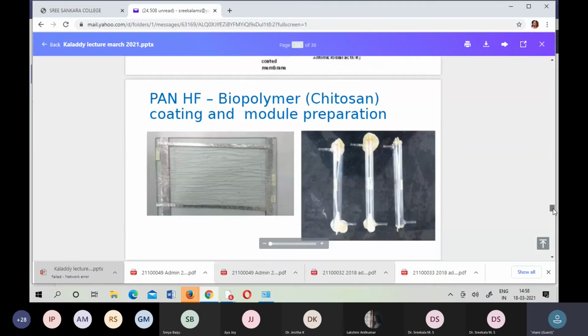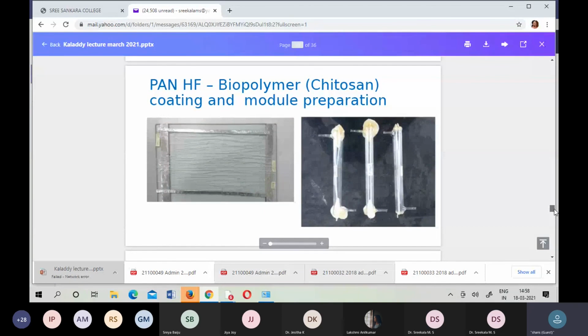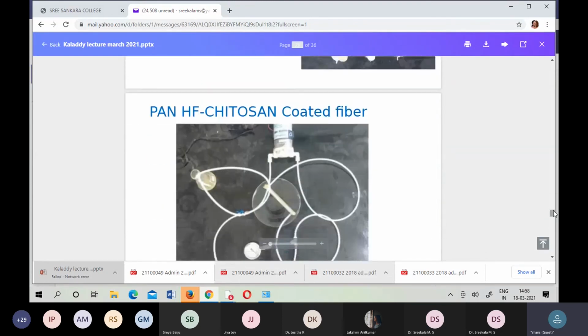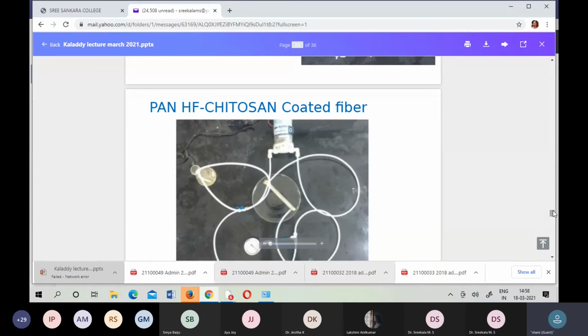Generally when you use only water, we get faster phase inversion and we may get a more dense membrane. But then in the last case we use DMF in water, 50-50. And the flow rate is also very crucial when you are making a hollow fiber. Flow rate in some cases is very high and in other cases very low, and that is the flow rate we maintain. The temperature is the last parameter that critically decides the phase inversion kinetics.